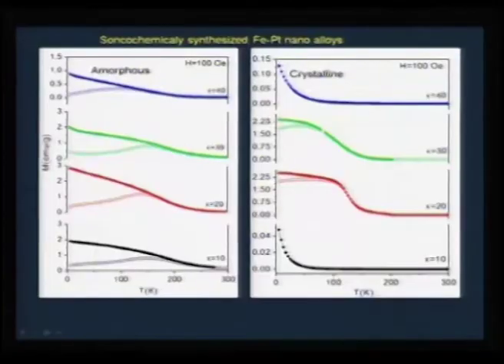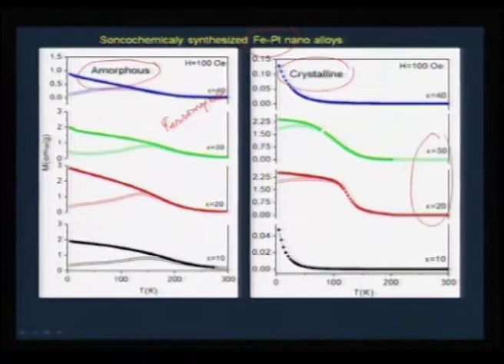alloys. For example, you take the case of FePt nanoalloy. As prepared nanoalloys are all amorphous, and you can see here the M versus T curve clearly shows that all the compositions are ferromagnetic in nature, because they show a typical ferromagnetic transition, whereas when you sinter these alloys, when they turn out to be crystalline, you can clearly see only these two compositions retain magnetism, whereas the 40 and 10% do not show magnetism.